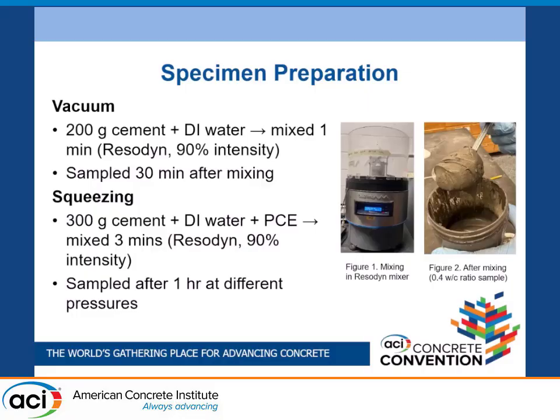We are mixing it for 3 minutes, because if we mix for just 1 minute, the paste will be relatively dry and there is no proper mixing of the samples. So we are mixing it for 3 minutes.